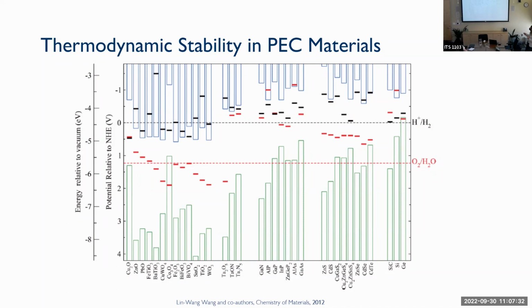And for simplicity now, I would just ask you to ignore this upper part and just focus on the lower part of this diagram. So if you look at bismuth vanadate, you see that the oxidation potential of the material is actually very close to the self-oxidation potential of the material itself. So the equilibrium for the holes to decide to go either to oxidize water or to self-oxidize the material is very small. Holes may decide to go either way because the two oxidation potentials are very close.